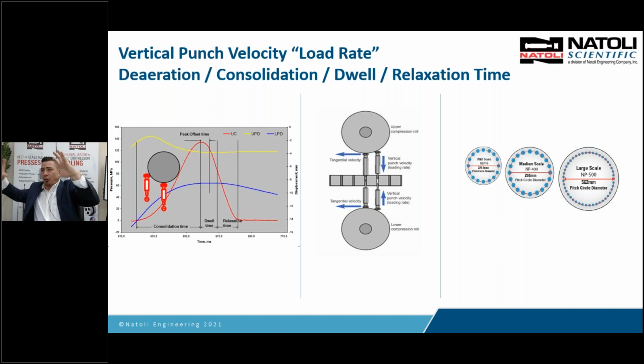Where if I had a large roll, that consolidation time is going to be much longer, but if it's got a 9.5 millimeter head flat, the dwell time is going to be the same. So even with a small roll and big roll, if your head flat's the same and your turret velocity is the same, your dwell time's the same. But what's different is for a large roll, you'll have more consolidation time, more time to tamp the air out and consolidate those particles. So the roller size is very important.